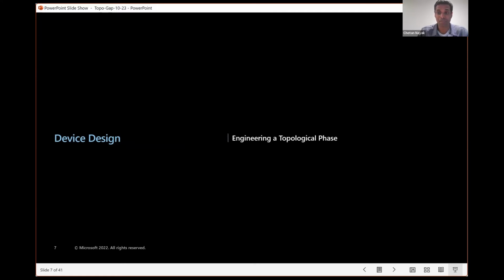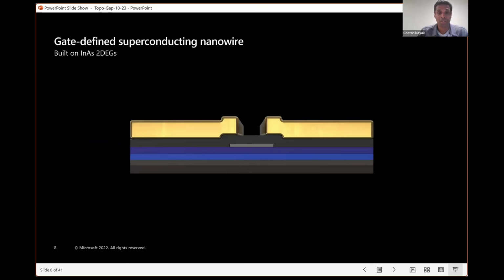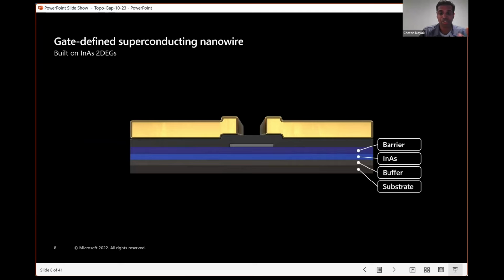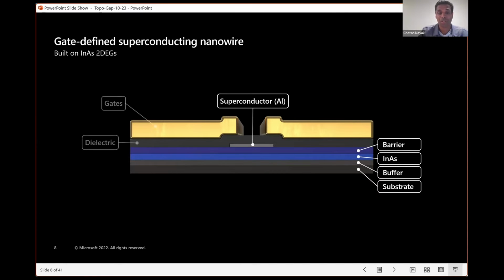How can we get something in reality that looks like that? Well, our approach is with gate-defined nanowires. These are built on indium arsenide 2-DEG. So this is a side view, cross-sectional view of our material stack. There's a substrate, a buffer, an indium arsenide quantum well, and a barrier layer. Okay. On top of that barrier, there's a superconductor, aluminum. So it's a very thin aluminum strip like this into the plane of the slide. That aluminum strip induces superconductivity in the indium arsenide quantum well. And there's also a dielectric and gates.